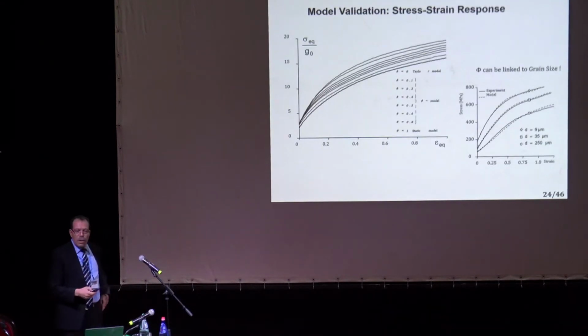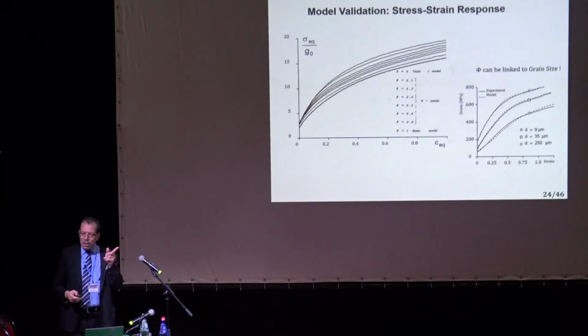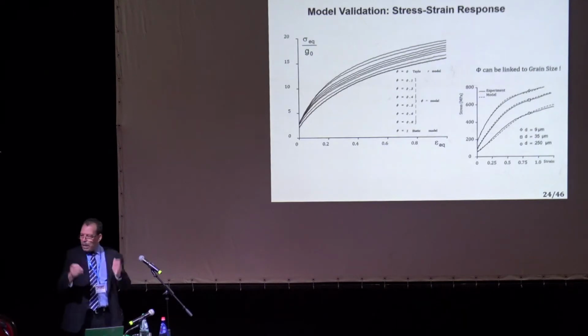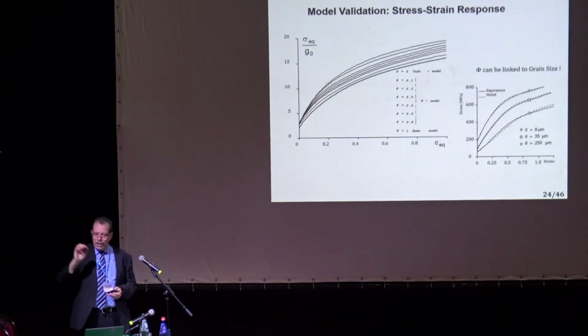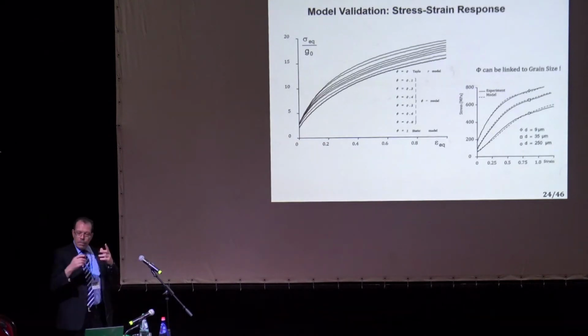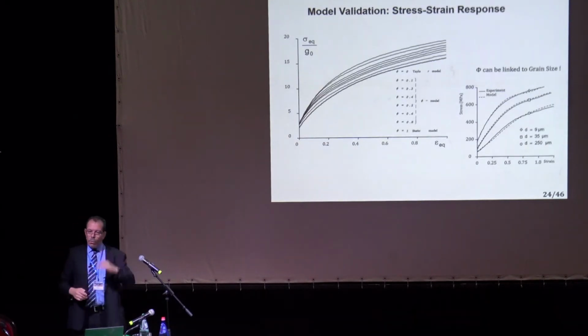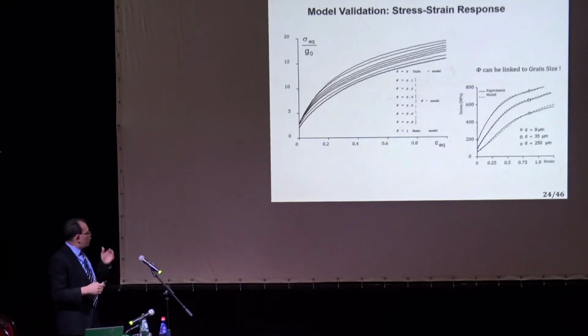Another thing is the stress-strain curve. Well, I did not start with the stress-strain curve because in these models, the stress-strain curve does not tell us much. Because you can use the hardening law in any way you want, put parameters there, and you can fit whatever you want. That's why I left it to the end, but we keep now the same hardening parameters for all models, okay, for different phi and for upper bound, lower bound with tangent or so. And this is what we get. This is the lower bound, this is the upper bound, okay, and this is for different phi.